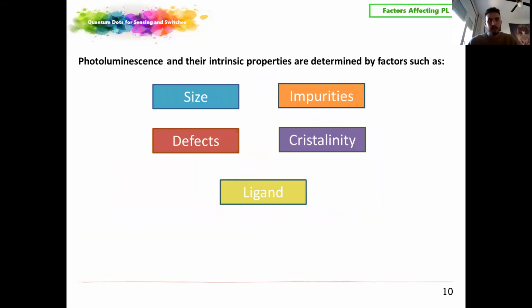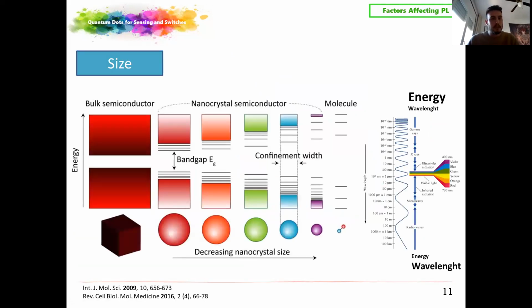Understanding this effect, we can see the properties of this kind of nanoparticles, where the most important properties to be controlled are the size, the impurities, defects, crystallinity, and ligands. Starting with the size, as I commented, it is so important because it can create a quantum confinement, which is necessary for the photoluminescence. When we are moving to a decreasing nanocrystal size, the band gap is increasing.